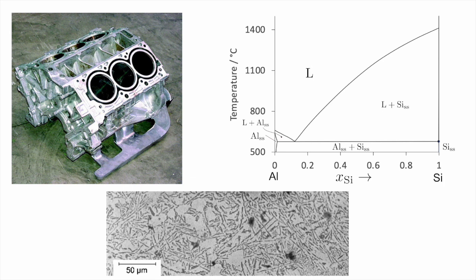This is the aluminium silicon phase diagram, and aluminium silicon alloys are used to make these engine blocks for internal combustion engines in cars. They used to be made of cast iron, but obviously this is much lighter. They have very good casting properties in terms of volume change and also the melting temperature, because they are slightly off the eutectic composition here. Perhaps about 10% weight of silicon.